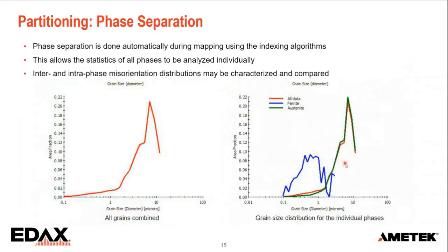And you can then also look at the grain size for each phase. So here, this is for everything. Then here on the right, I've made a multi-chart where you can see the austenite and all data. It's almost the same because there's so little ferrite available, but the ferrite grain structure on average is a little bit smaller than 1 micron, where the austenite is about 10 micron. So you can quite easily tell those apart.